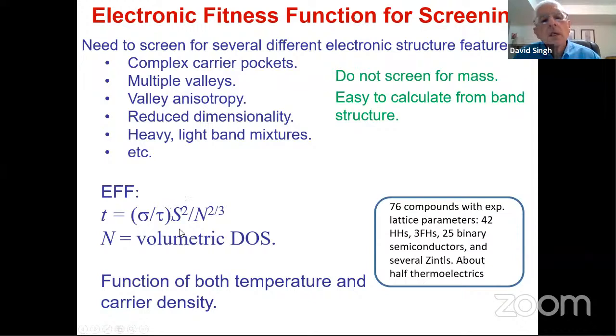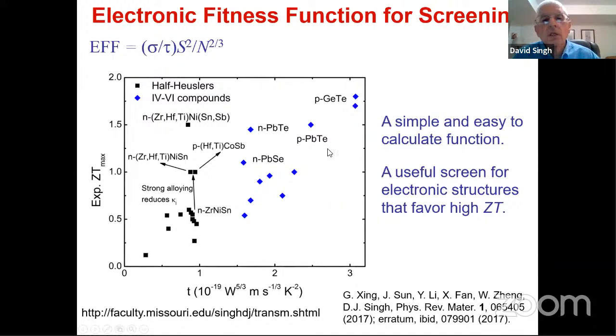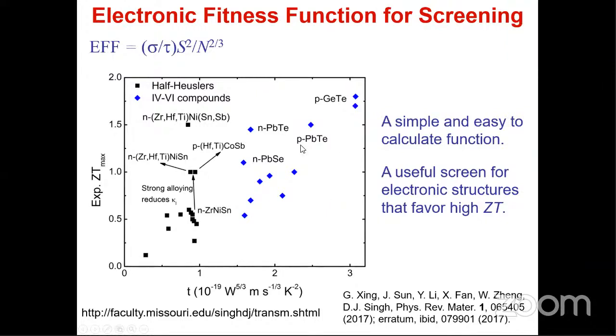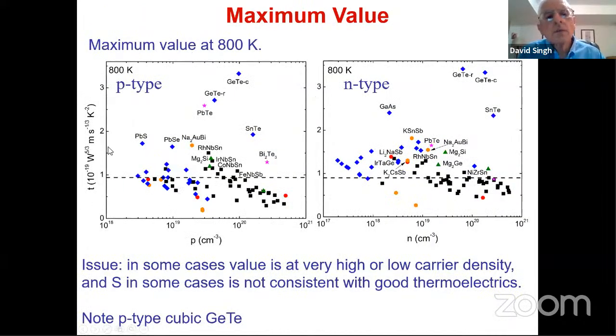This is the Seebeck coefficient that I showed you before. You can calculate that. And N is the density of states per unit volume, which you can also calculate. And this 2/3 power is in order to achieve a behavior that would be consistent with what's expected for electron phonon scattering, with some modification that I'm not going to discuss. But we just tried it. So this is this function T that you can calculate from the band structure.